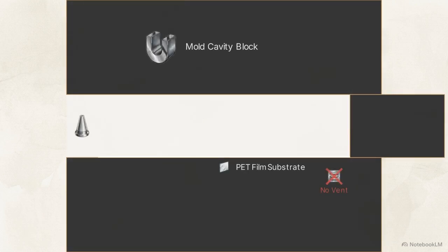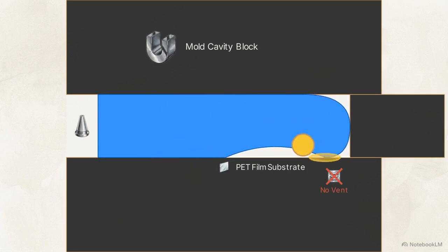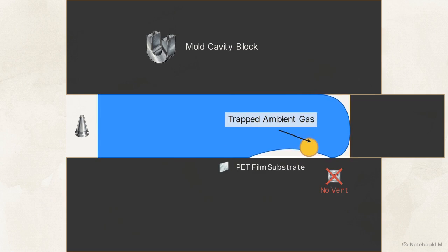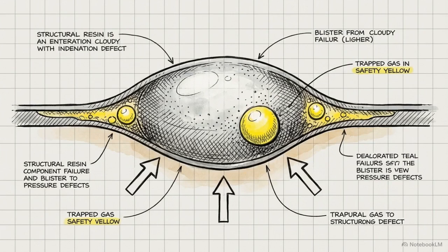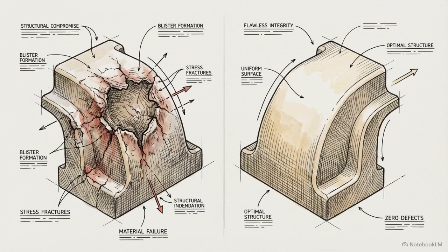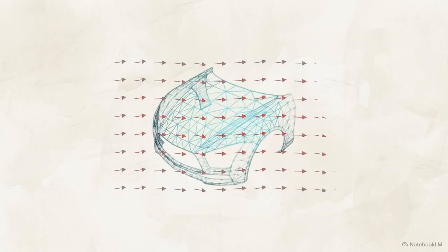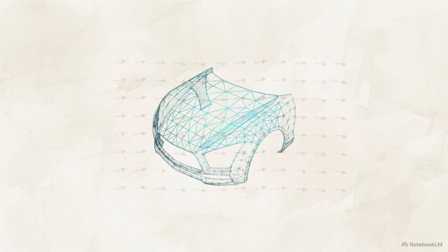This simulation shows the primary fluid dynamic challenge. The rapid liquid melt front risks pressing the thin film against the mold wall too early. When the plastic prematurely seals the edge, remaining ambient gas has nowhere to go, trapping directly against the film surface. This trapped gas causes a defect known as a gas mark, ruining the visual and structural integrity of the finished surface. To prevent this, engineers use complex fluid dynamic simulations to map the exact flow path.